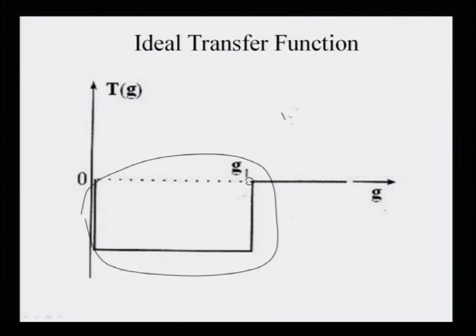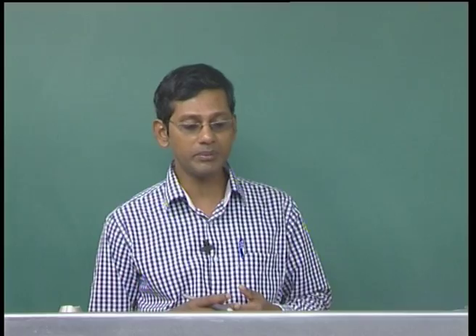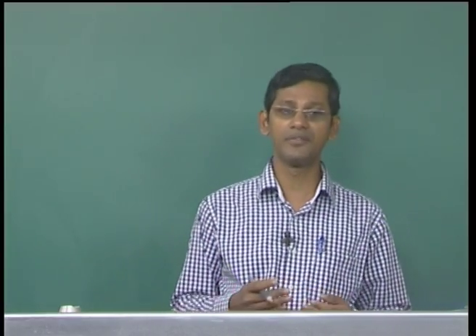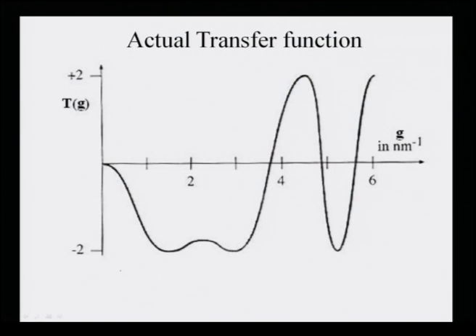This kind of situation is never really achieved, because all these microscopes will have defects, and the defects change this transfer function drastically. I am showing you one such picture where the actual transfer function, Tg as a function of g, is shown, and Tg values can vary from plus 2 to minus 2. But what you can see is that there is a lot of variation: not only has the number of zeros increased in this transfer function, but the values also change depending on the spatial frequencies.